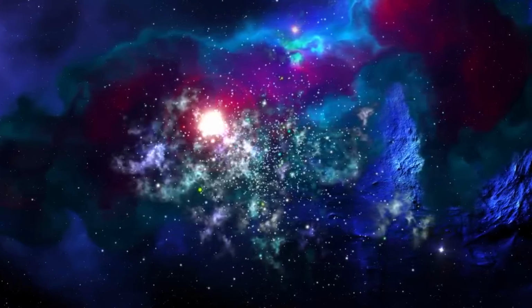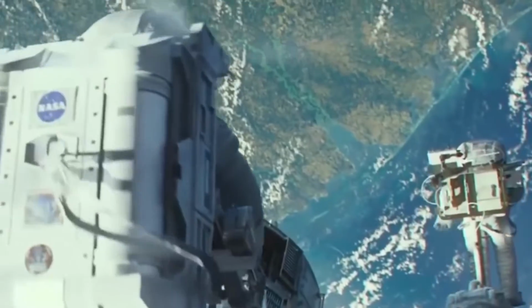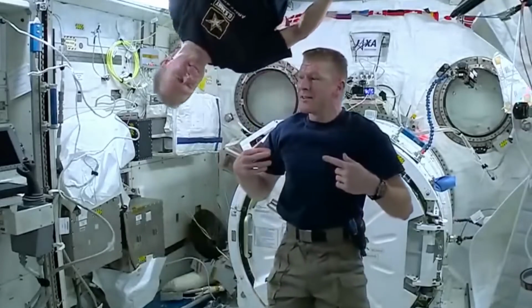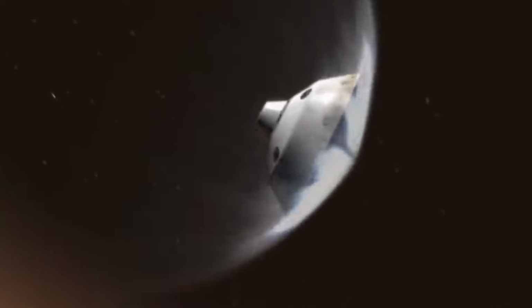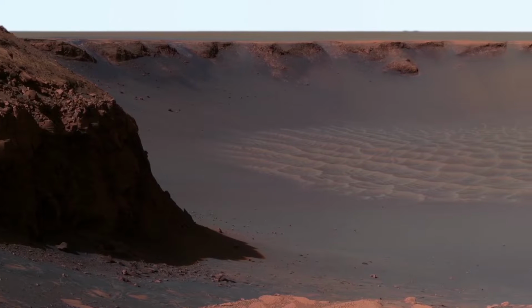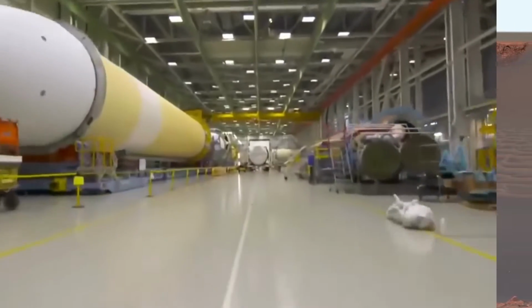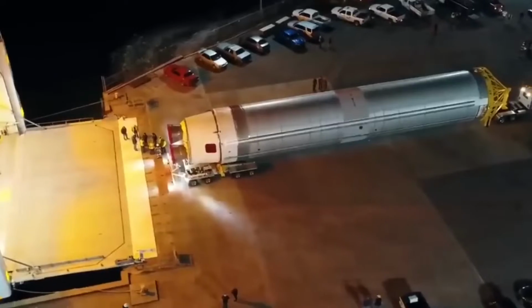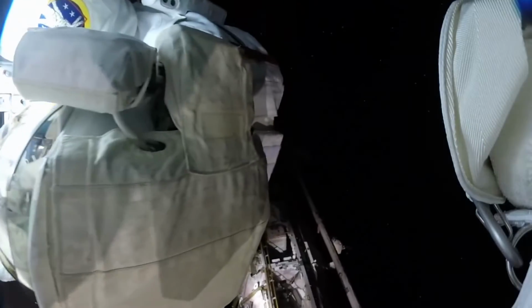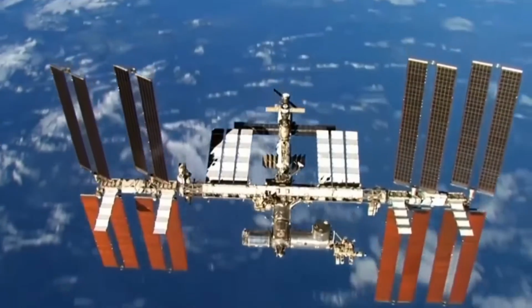But if you're still puzzled by what corrosion is and why it is a cause of concern, we'll run you through the basics. The effects of corrosion in orbit are greatest for spacecraft with moving parts. Early satellites frequently experienced issues with losing their bearings. Now, a small layer of gold is applied to the bearings. Different materials have varying levels of space corrosion resistance. Atomic oxygen, for instance, slowly corrodes aluminium, whereas gold and platinum are more resistant to corrosion.